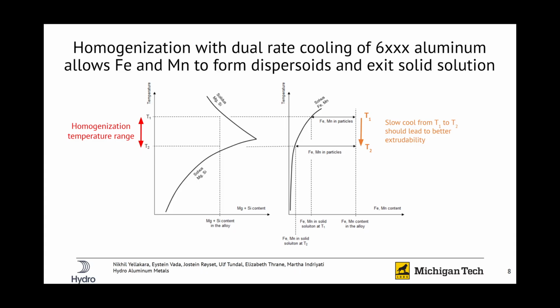consistent extrudability. In our homogenization treatment, we're concerned about 2 main microstructural features: a magnesium silicon forming precipitate phase called magnesium silicide, and the dispersoids that form out of iron and manganese. As you decrease the homogenization temperature, the iron and manganese in solution decreases as you form more dispersoids, but if you drop it below the solvus line of the magnesium and silicon line, it will end up forming more magnesium silicide precipitate out of solution, which you don't want for consistent extrudability.